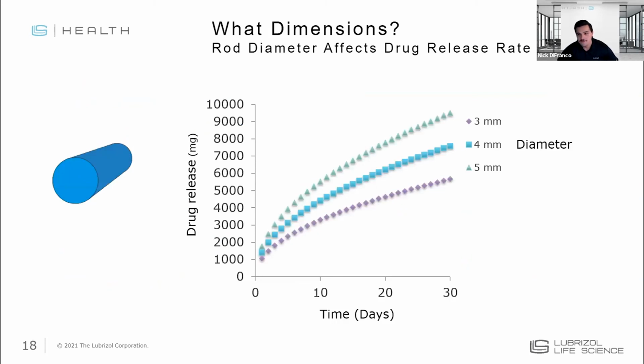And so once you've settled on a design that you want to work with, dimensions come into play. Obviously, where the implant is going to play a big role here. If it's going in the eye, the dimensional considerations are completely different than a subcutaneous implant that goes in under the skin in the upper arm. But as you change, say, the diameter of a rod-shaped implant, you're also changing the surface area through which drug can diffuse, and creating an impact on drug release by doing so. So it's important to evaluate this and settle on a dimensional specification early on in a project.